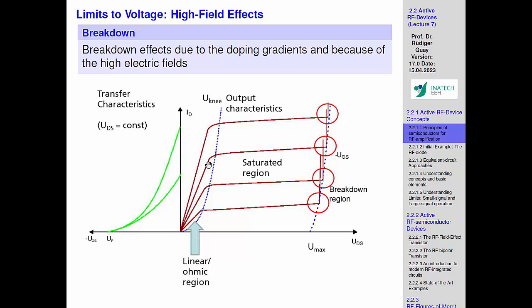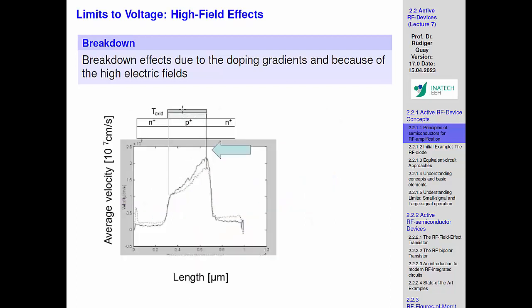Yeah, because when we look at the cross-section of a MOSFET, which we'll explain in a minute again, you see that even for relatively large MOSFETs, the maximum velocity of these electrons happens here at the drain side of the gate. Yeah? Because the electrons get the maximum energy when they're accelerated exactly there. And this is not only because of the acceleration between source and drain, but also because there's a doping profile change. Yeah? So especially these changes in the doping profile create very high fields. So it's local. Yeah? So the oxide, apart from starting leaky because it's getting small, this is combined with the electric field focusing at some point.